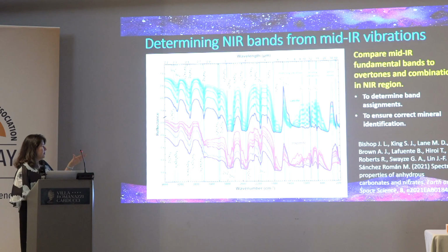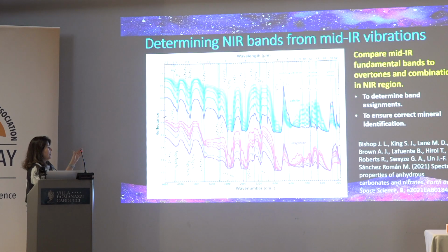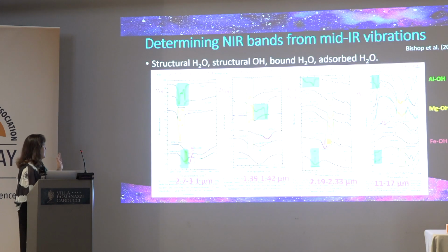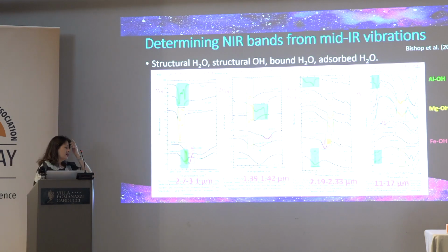So something I've done with other minerals too, this is a carbonate study, is look at the bands in the mid-infrared region, so the stretching and bending vibrations, and in this case these are both calcium carbonates but with different structures, and I looked at different grain sizes and then figured out the band assignments for these combinations and overtones. And for clay minerals there's not quite so much going on, but still you can look at the stretching and the bending vibrations and then combine these for the stretch plus bend and multiply this by 2 and an offset factor to get the overtone. So by looking at the mid-infrared and the near-infrared together, we could confirm that what we're looking for is actually there.